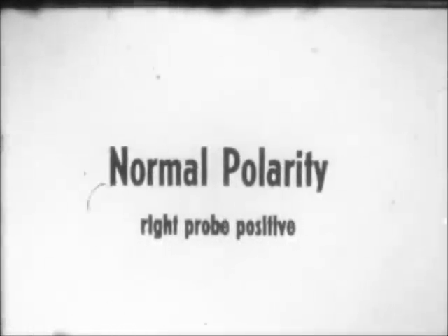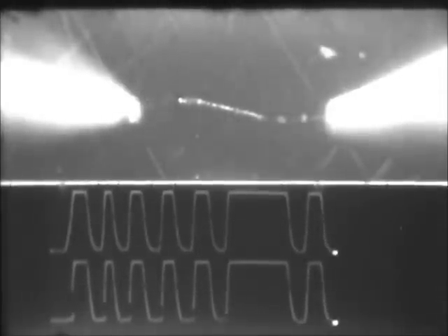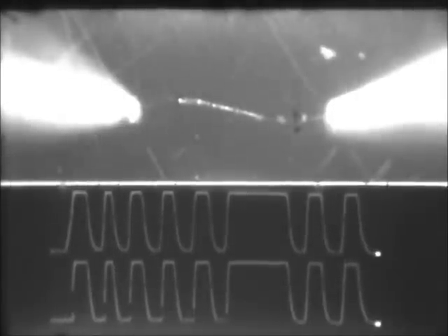We are going to show that the filament growth is due to an electric field effect. As the filament grows from the right, the threshold voltage decreases correspondingly as the distance between the tip of the filament and the left probe decreases. Therefore, it is a constant electric field that is driving the filament growth. As we vary the voltage, it took 9 pulses to complete the filament growth, as indicated by the step jumps in the current trace.